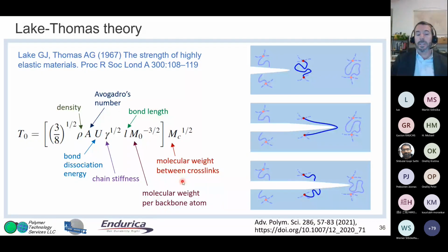The first one is crosslink density, right? That's explicitly in the model. The other one is molecular weight per backbone atom. That has to do with the repeat unit of your polymer, chain stiffness, also a backbone polymer chemistry, bond length, bond dissociation energy. All of these relate to the building blocks for the backbone of the polymer.